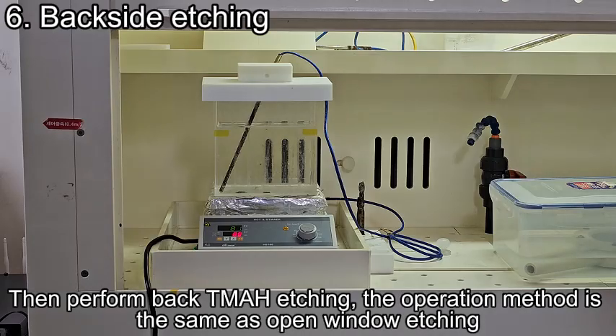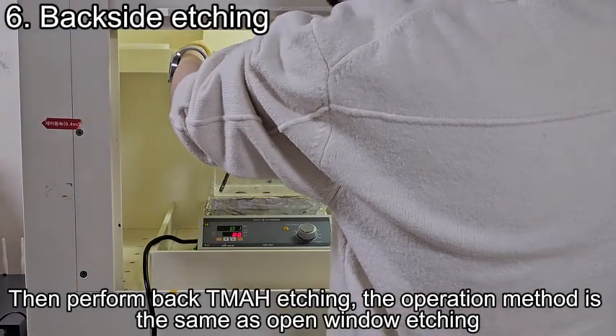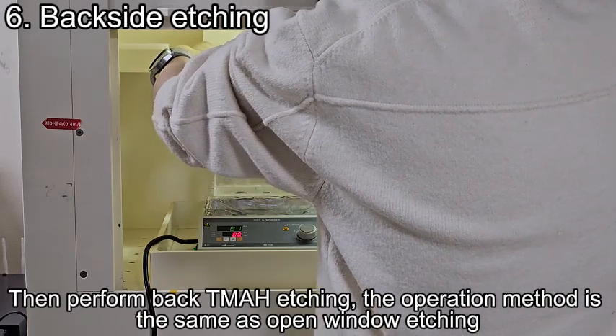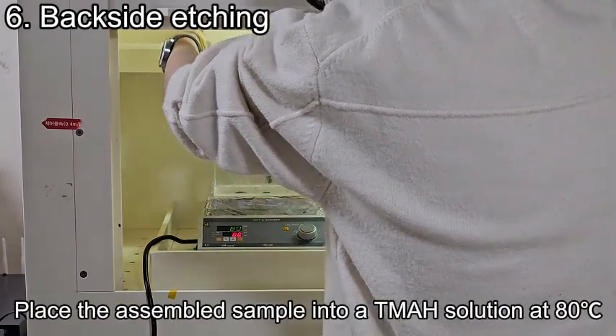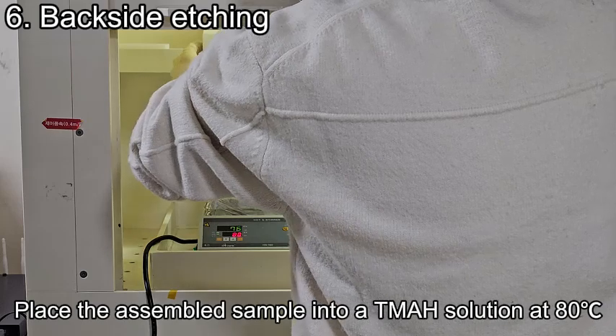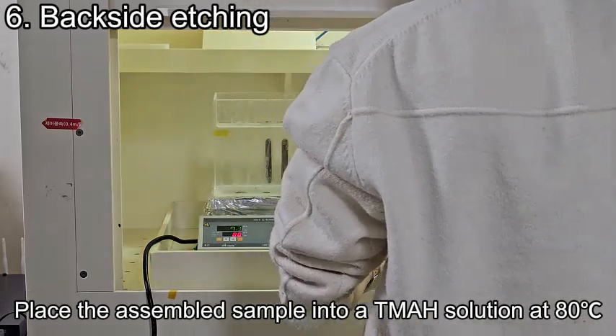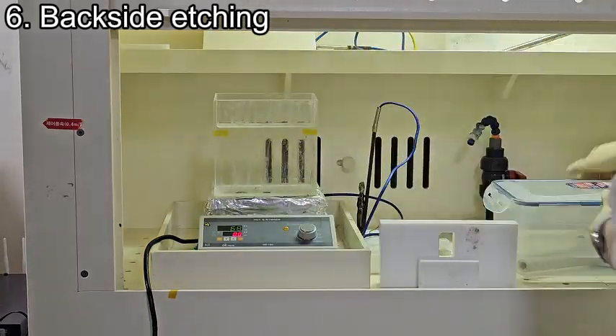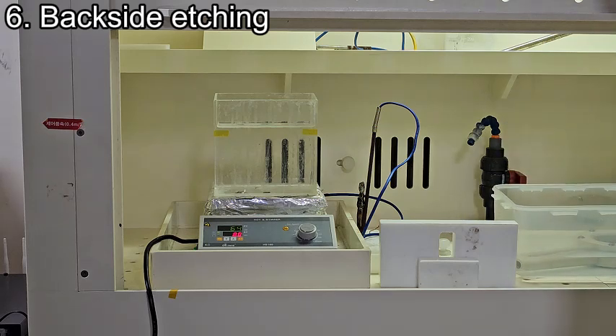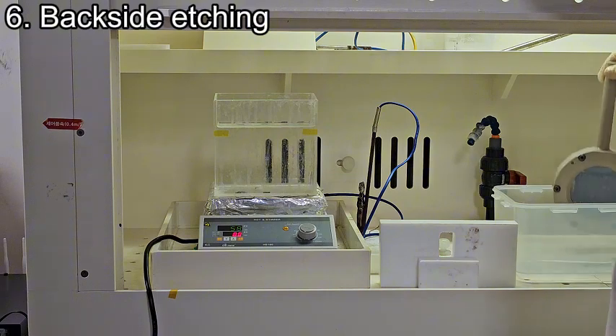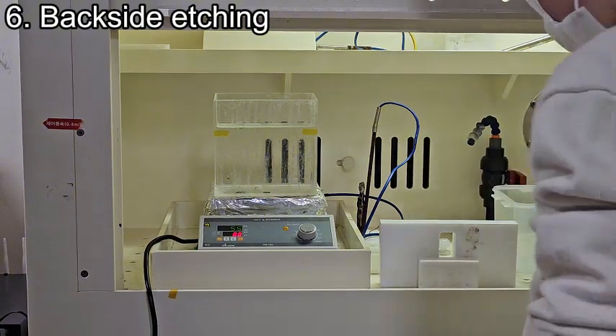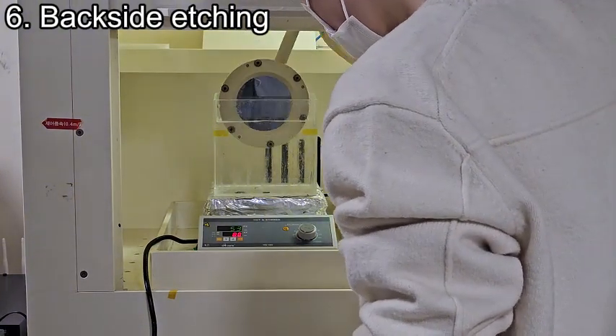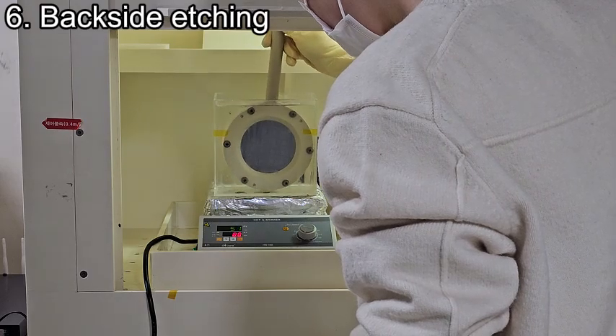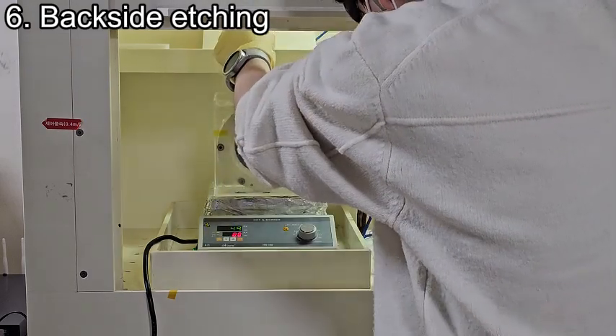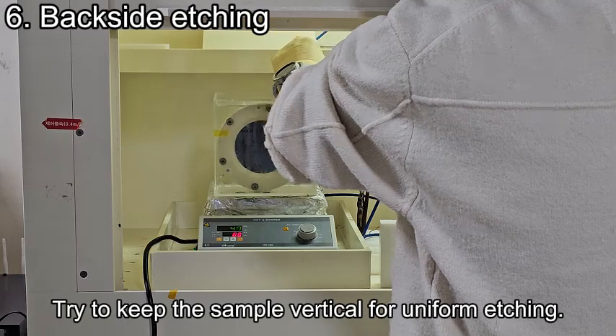Then perform back TMAH etching. The operation method is the same as open window etching. Place the assembled sample into a TMAH solution at 80 degrees centigrade. Try to keep the sample vertical for uniform etching.